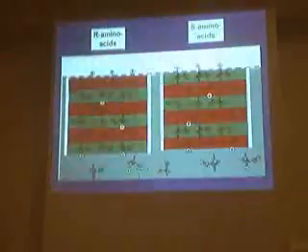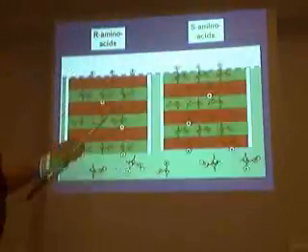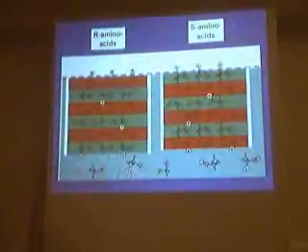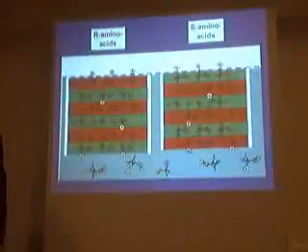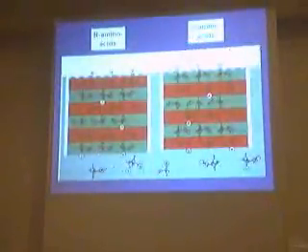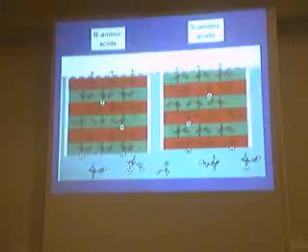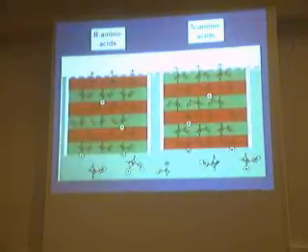Okay. So you see, if we have, let's say, the R, in the experiment you only put R amino acids or S amino acids. You don't mix them. I will tell that later on. I can mix them together, but I want first of all to make the first point much clearer. The experiment that I'm doing now, I'm putting 1% of R amino acid into the solution, or 1% of the other. Okay, and this was actually the two-dimensional chirality. If you put 1% of S, you get S, if you put 1% of R, you get R.